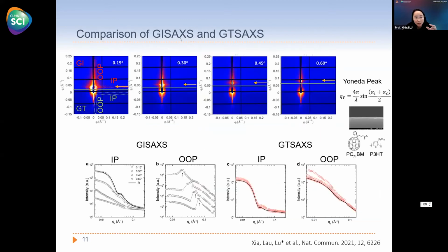So by this way, we can get the direct comparison of GISAXS and GTSAXS in the same scattering pattern. So this line just separates the surface horizon, and when we gradually increase the incident angle, we can see that this Yoneda peak was lifted off, and we can get a symmetric scattering pattern below the horizon. And by fitting the scattering pattern both in-plane and out-of-plane, in GISAXS the in-plane domain separation feature we can extract as in convention, and by GTSAXS we can get a similar structure. In the out-of-plane direction, this peak is from the Yoneda peak, which is unwanted. But for GTSAXS, now we can also get a clean scattering feature from our domain size.